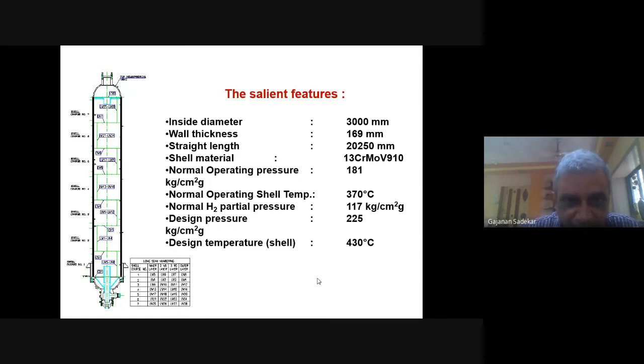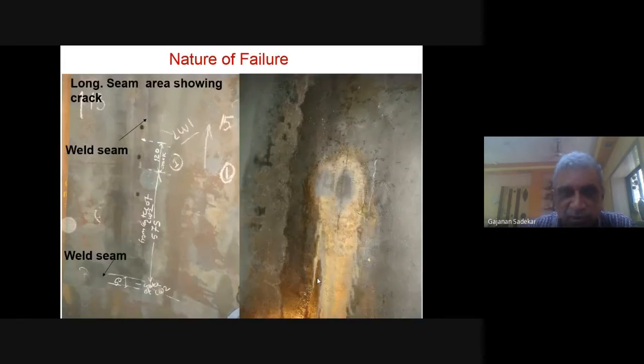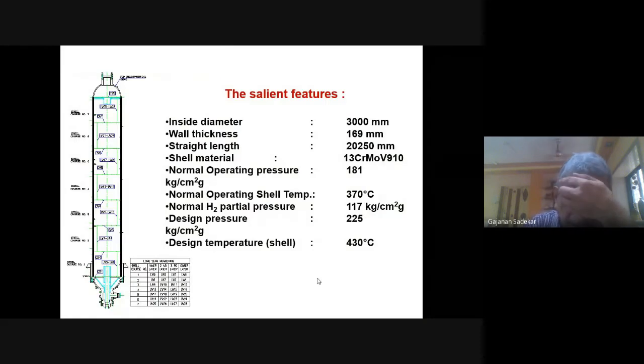Operating temperature, design pressure was 225. Operating temperature is, I think, around 370. Yes, operating temperature 370 degrees centigrade. So this is the equipment, as I told you, working with an inside catalyst and a gas mixture of hydrogen, nitrogen, and ammonia. So what happened, I'll tell you, when this equipment was supplied, after something like 1.5 years,